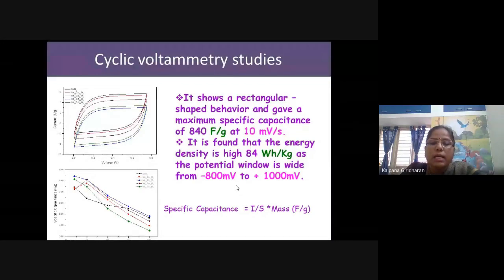SnO2 by using cyclic voltammetry, which gave a maximum capacitance of 840 farads per gram at 10 millivolts per second, with an energy density of 84 watt-hour per kg, at a high potential window of 0.8 to 1 volt.